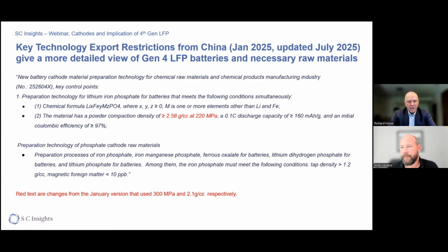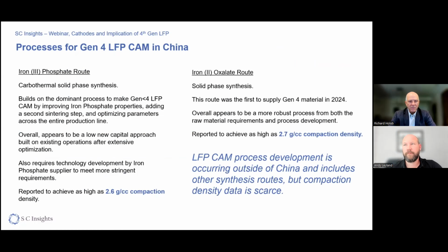A little typo here, but the numbers that changed from January to the July output: the 220 megapascals was reduced from 300 megapascals, so that actually is now a more stringent requirement. And in the original version, the tap density of the iron phosphate being 1.2 grams per cc was actually listed as 2.1. I'm pretty sure that was just a switching of the numbers, but not necessarily a tighter restriction. And I'll mention that magnetic foreign matter is a very difficult thing to measure, especially in paramagnetic salts like iron phosphate. And the procedure for doing that is still not well defined, and I'll talk about that a little bit later. Next slide, please, Andy.